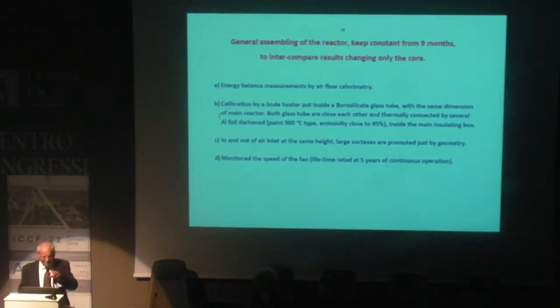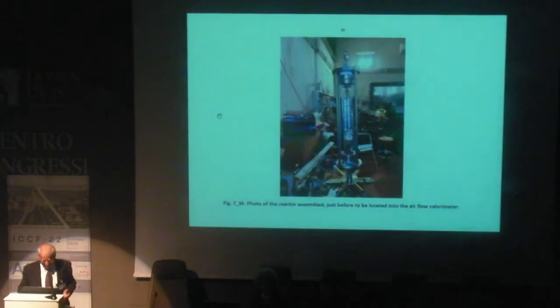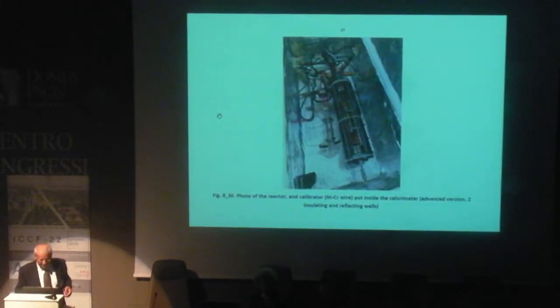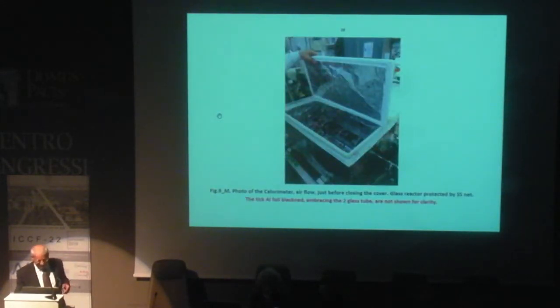The energy balance is made by airflow calorimetry, very, very simple. Input and output on the same side, just crossing to increase turbulent air. Very simple, nothing special really. Here is a photo of the reactor before mounting the 3 wires, the 3 cores. The tail of the reactor inside the insulating box before closing. And moreover, to have homogeneity with respect to the calibration, we put thick black aluminum foil to have a more homogeneous temperature.